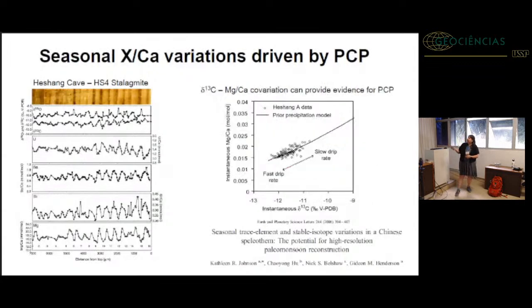And so one other way to potentially identify PCP is if you see covariation between magnesium, calcium, and C13, that can sometimes be evidence because as that PCP is proceeding and you're degassing, you're preferentially losing the carbon-12. And so you might expect this sort of correlation, which is what we found here in this Heshang Cave